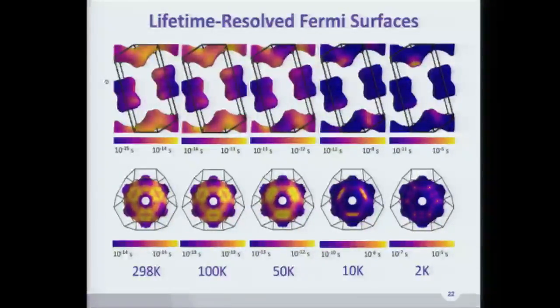So here on top, we're looking at the Fermi surfaces as a function of temperature for tungsten phosphide. The bottom is a more conventional Fermi surface for copper. You might have seen this in Ashcroft-Mermin or your favorite solid-state class, going from room temperature to pretty low temperature. And what you see is that not only do the lifetimes span many orders of magnitude, but also for tungsten phosphide, there are a couple of spots that remain suspiciously different looking than other parts. Again, we wanted to get at the question of what is leading to the violation of the Wiedemann-Franz law. The lifetimes tell us half of the picture, but maybe there's something from the Fermi surface that we can mine out that tells us why the Wiedemann-Franz law is being violated in these materials.